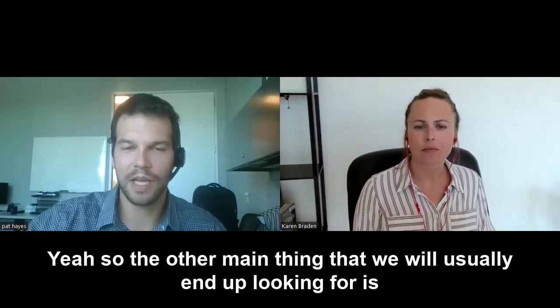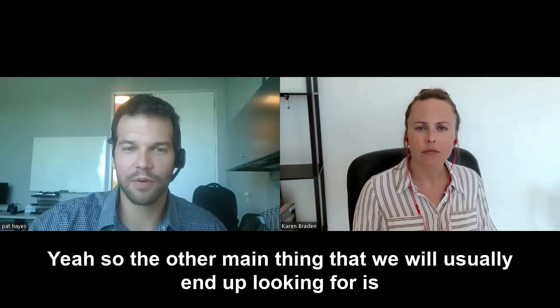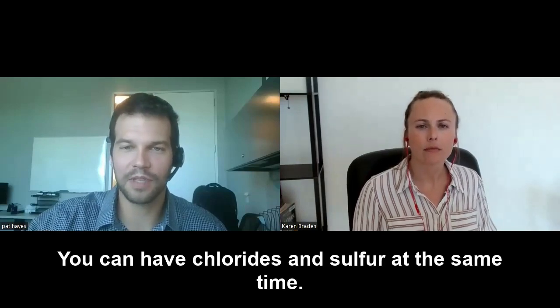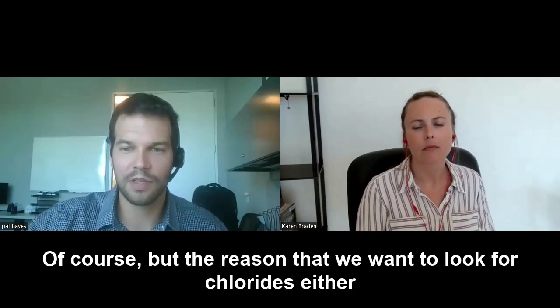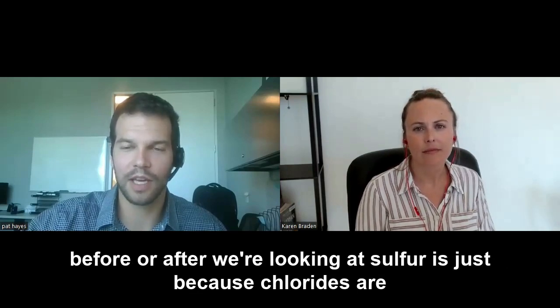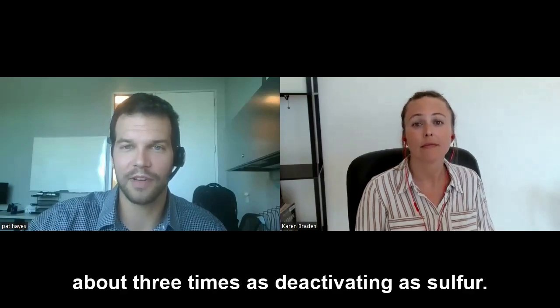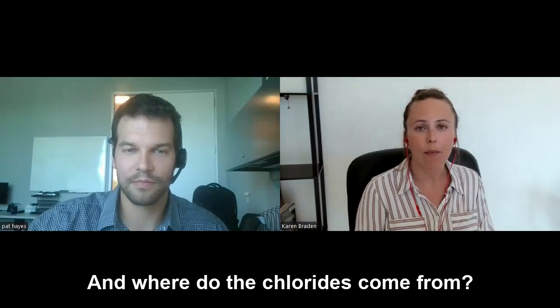Yeah, so the other main thing that we'll usually end up looking for is chlorides. You can have chlorides and sulfur at the same time, of course, but the reason that we want to look for chlorides either before or after we're looking at sulfur is just because chloride is about 3 times as deactivating as sulfur. Wow. And where do the chlorides come from?